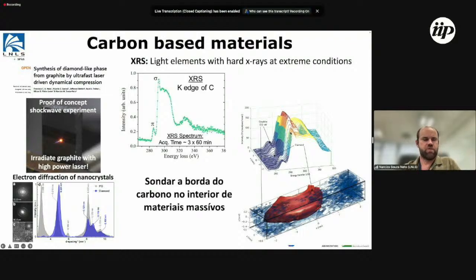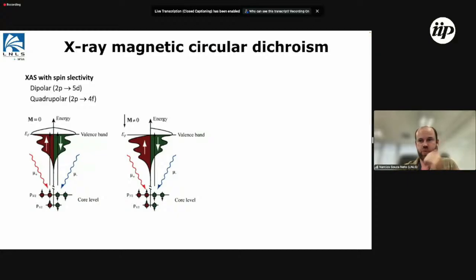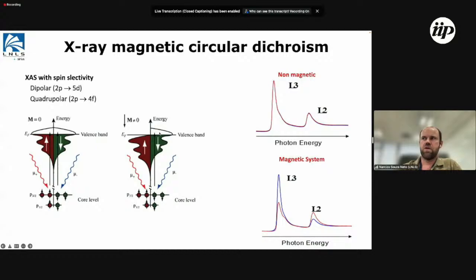But so that is for carbon materials, but then let's say, what about magnetic materials? Actually, that we can probe as well. If we look at X-ray magnetic circular dichroism, where we excite the core level, like 1s, 2s, and promote those electrons to the continuum. But then when we have the circular polarization and apply a magnetic field, there is this imbalance of the spin density of states. And when we measure the spectroscopy,